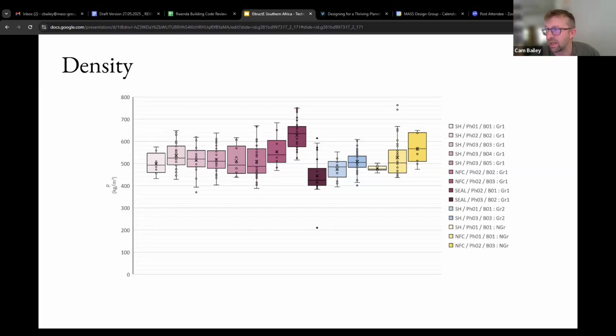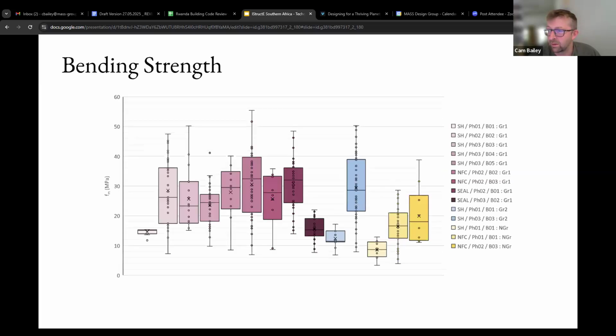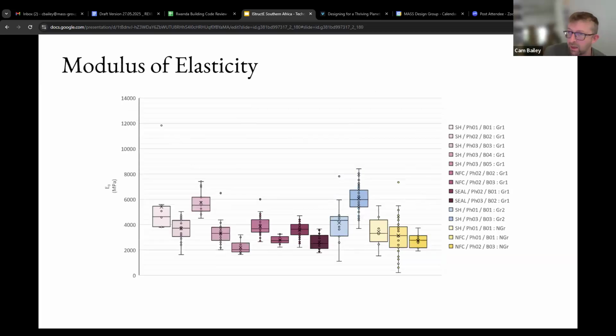And so, as you can see here, the density actually came out pretty consistent across all batches and all grades. Roughly around 500 to 550 kilograms per meter cubed, which is high for a softwood, and again backs up why we thought the timber might be a bit stronger than it was. But as you'll see, if I go to bending strength first, the bending strengths we got were relatively consistent across grade one and grade two, but less so against the ungraded timbers. But when we worked out our characteristic values, because of the large spread we saw in the results, we ended up getting basically 10 to 12 MPa characteristic bending strength that we were allowed to use. Then in terms of the modulus of elasticity, we saw quite a lot of variance in the batches.